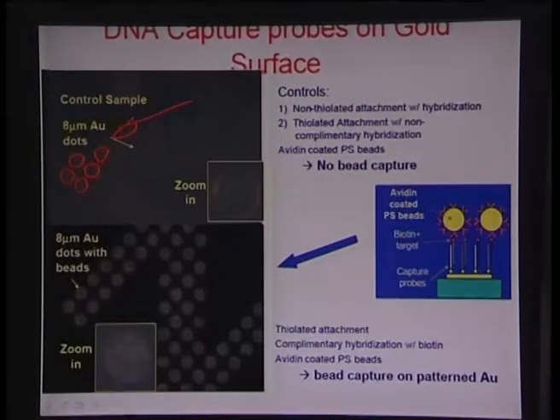Okay, so these dots here that you can see are 8 micron gold dots, made of gold. And what we do here is that in some of the dots we do not bind any capture probe, and in others we do bind capture probes. So essentially you are making some control and some reference sites of binding. Wherever there are dots which have the presence of the capture probe, there is always a capture of the polystyrene beads, as can be seen here in the close up view. These small moieties here are the tiny polystyrene beads which have gotten captured because of the presence of the capture probe. So optically, using an optical microscope, you could realize whether there is binding going on between the target DNA and the capture probe just by looking at whether these gold dots have polystyrene beads or not.